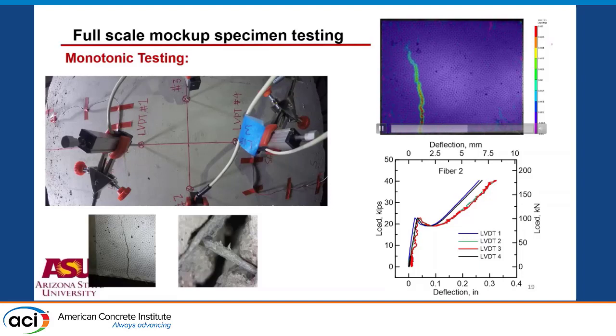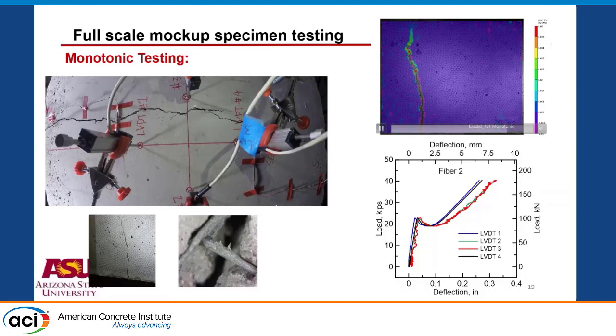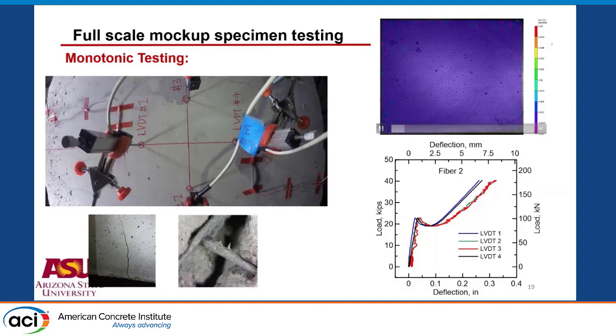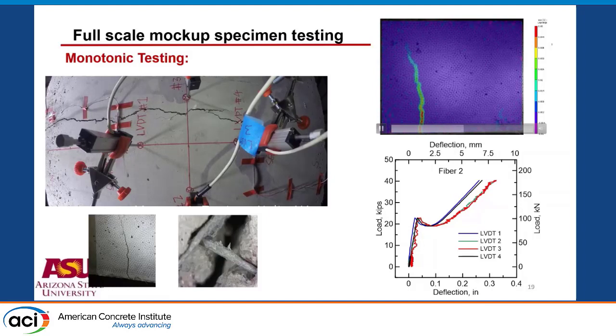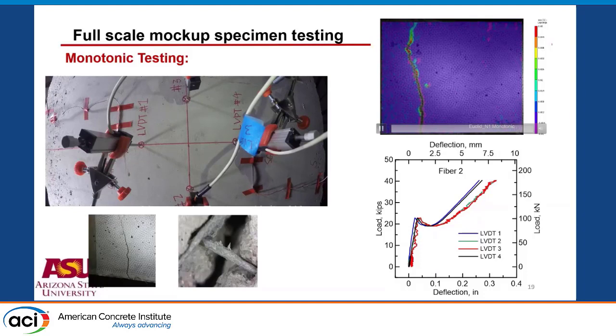So within this specimen, we can clearly see this is quantitative work, which means that you can measure the crack opening and correlate it with the load. So you basically develop this loop type of mechanism where you collect the data and allow for measuring the level of contribution of steel rebar versus the other one.